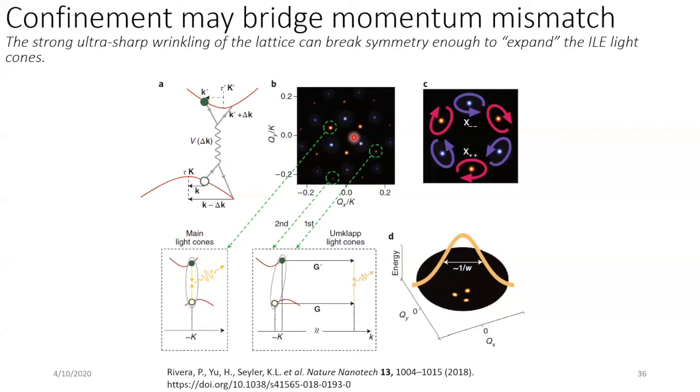You need to have some sort of bridge to bridge that momentum mismatch. This can be provided maybe by interaction with a phonon or maybe the moiré lattice, which is a beat pattern that forms when you have a mismatch of the lattice constant or a twist in the two constituent crystals. What strain might do, in particular what a wrinkle might do, is it gives you maybe a scattering signature. It'll act like a point defect and maybe blur out these light cones a bit, giving you access to more momentum vectors. But it also breaks symmetry very strongly in the crystals. So maybe much more of this space is optically bright. So we basically expand the light cones of the interlayer exciton and make them bright.